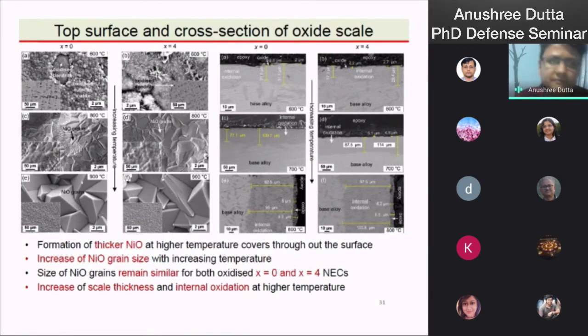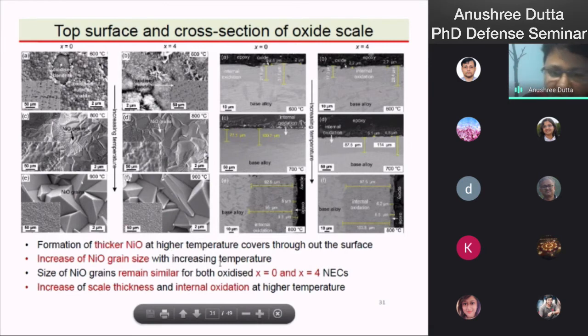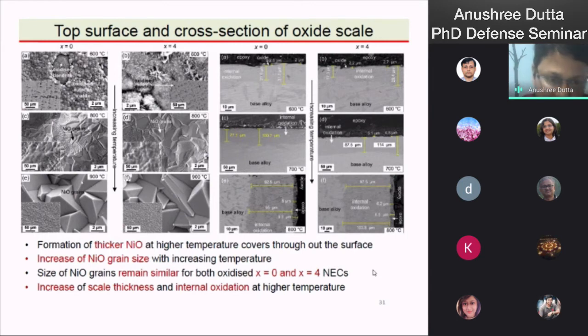As gamma nickel and Ni5Zr have different oxidation resistance, the gamma nickel dendritic phase surface can be distinguished even after oxidation at 600 degrees centigrade. Whereas with the gradual increase of thickness of the oxide layer, at higher temperature the oxide fully covers the outer surface of both the gamma nickel dendrites and the eutectic matrix. NiO grains increase with increase of temperature, and the size of NiO grains remains similar for both X0 and X4 NECs. Thickness and internal oxidation increase at high temperature.